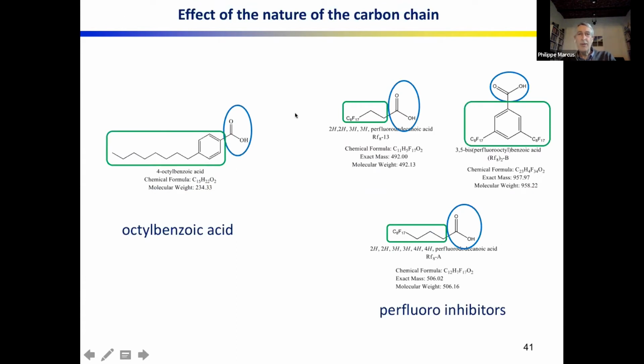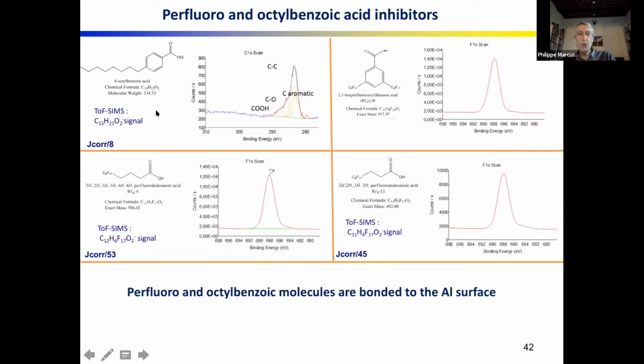Now we looked at the nature of the carbon chain for some other molecules, octyl benzoic acid, and we also looked at perfluoro inhibitors for comparison. So to make a long story short, we look at the fluorine 1s spectrum for the perfluoro molecule because it's a very good marker of the presence of the molecule. And in these three cases that I'm showing with my pointer, you see that we have a fairly intense fluorine 1s peak, which means that all these perfluoro molecules are well adsorbed and bonded to the aluminum surface. And this is also the case for this octyl benzoic acid, according to the presence of these two CO and COOH functional groups.